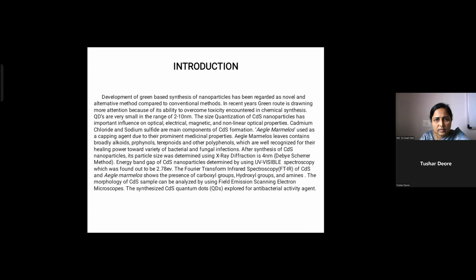Quantum dots are very small, in the range of 2 to 10 nanometers, ma'am. And I used Aegle marmelos, meaning bael leaf, as a capping agent. I took several characterizations for that: XRD with Cu K alpha radiation of 1.54 angstrom, FESEM, UV-visible spectroscopy, and FTIR for both Aegle marmelos and the synthesized CdS quantum dots.